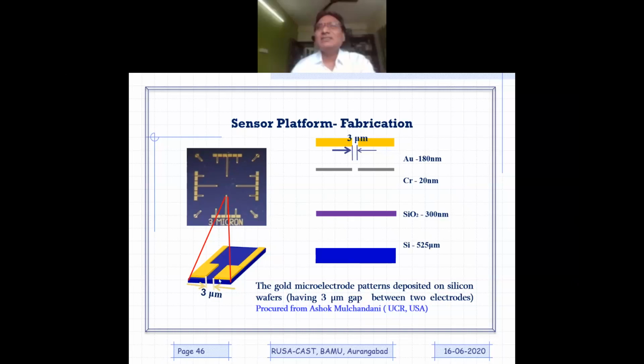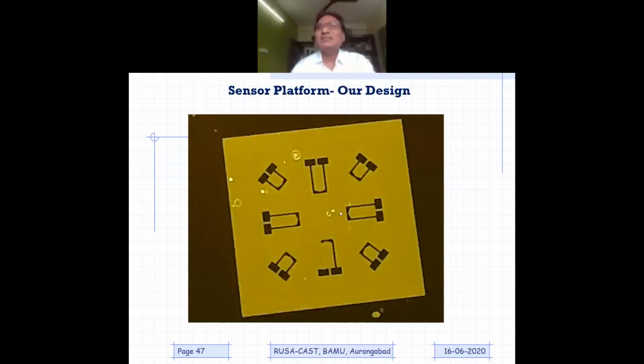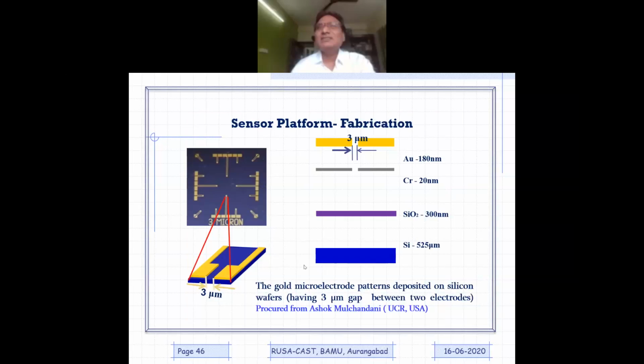As far as selectivity is concerned, of course, you can decorate CNTs with various metal nanoparticles, because metal nanoparticles are going to be good for inculcating selectivity, so you can address this issue. But even if you are decorating CNTs with metal nanoparticles, that honeycomb structure is still going to be exposed to the analyte, and then you are still going to have a recovery problem. Although you can address selectivity, you will still have the recovery problem.